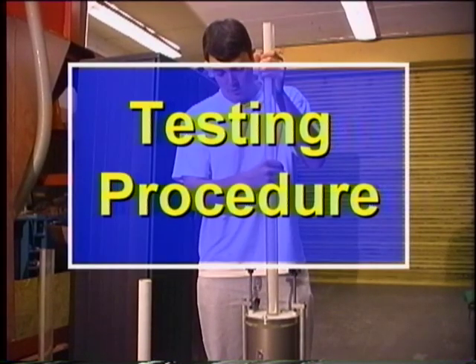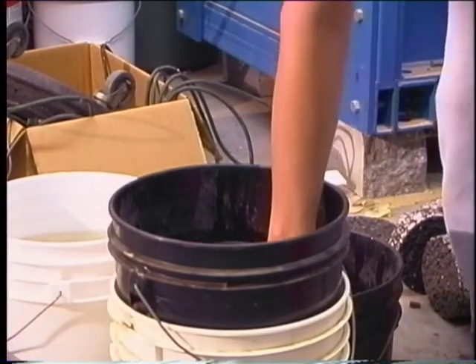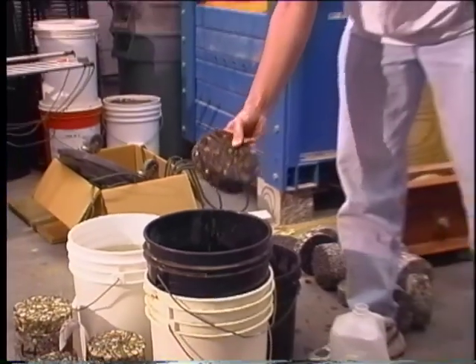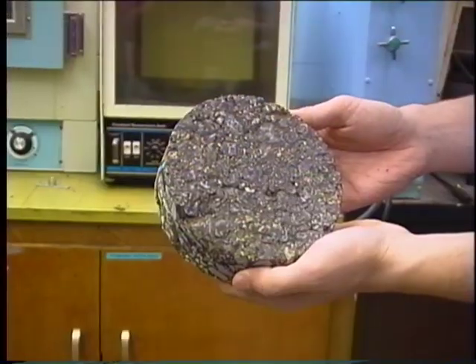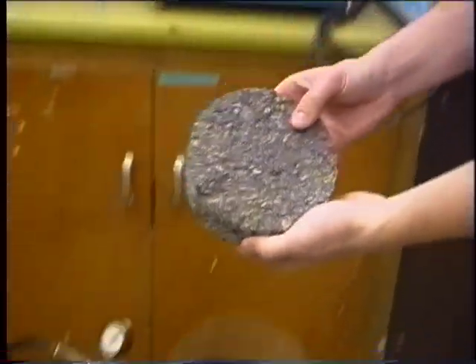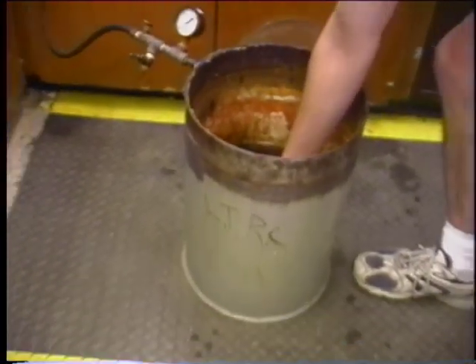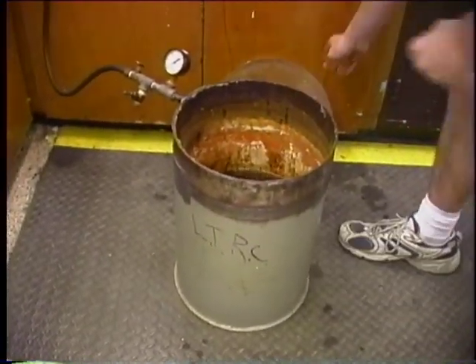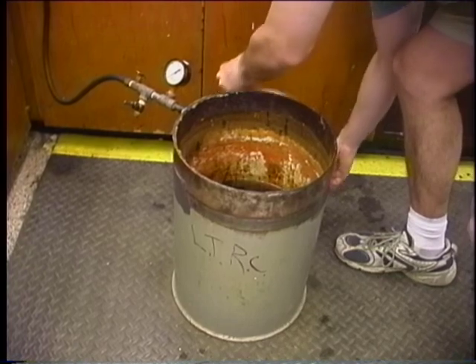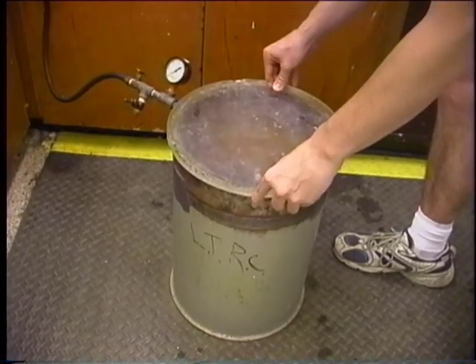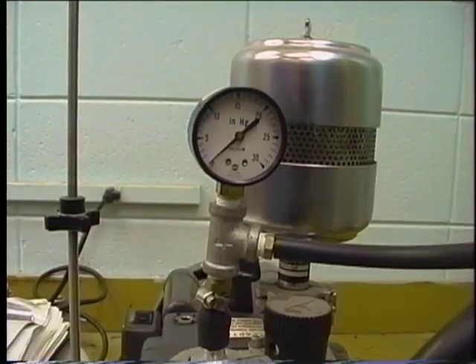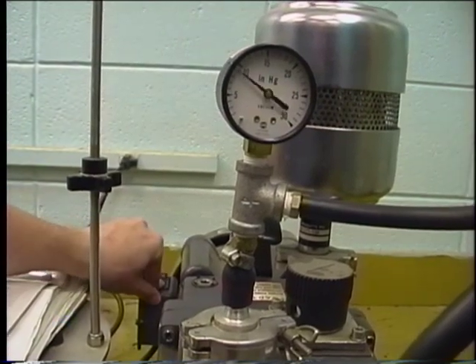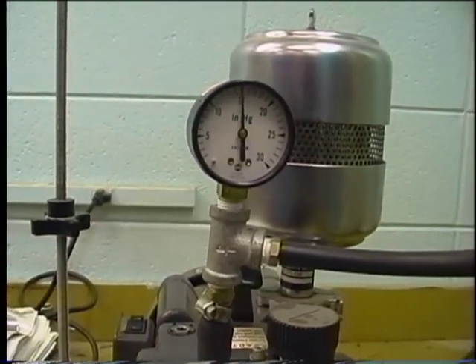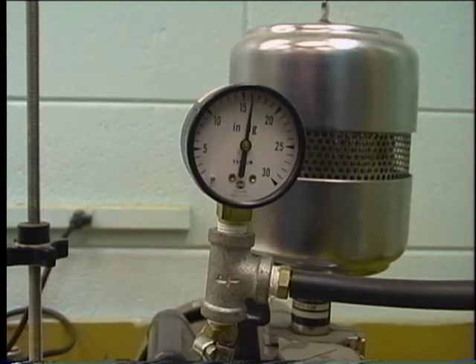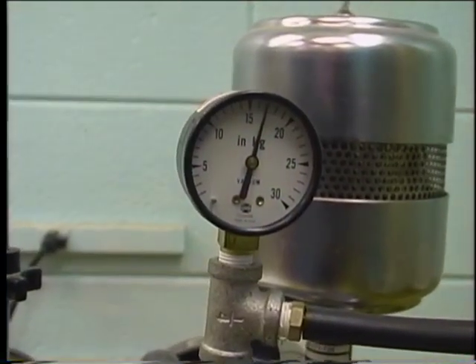The testing procedure is performed as follows. Submerge samples in water overnight to assure saturation. Vacuum saturation may also be done to saturate the samples. Vacuum saturation is done by placing the sample into a vacuum chamber filled with water and connecting a vacuum of at least 28 inches of mercury to it for 15 minutes. The sample is allowed to stand in water for 10 minutes after the vacuum is removed. This removes any trapped air that may be in the sample.